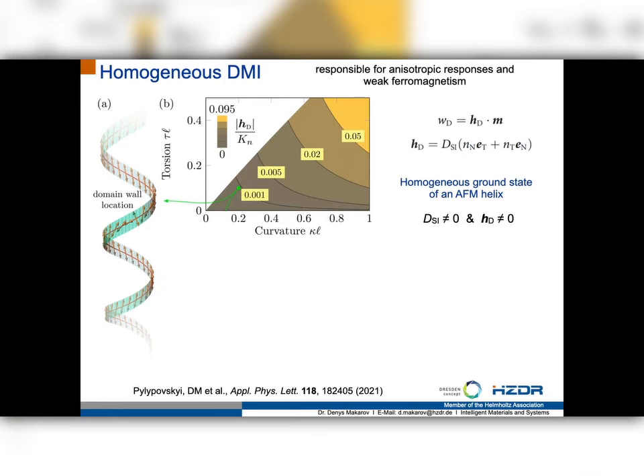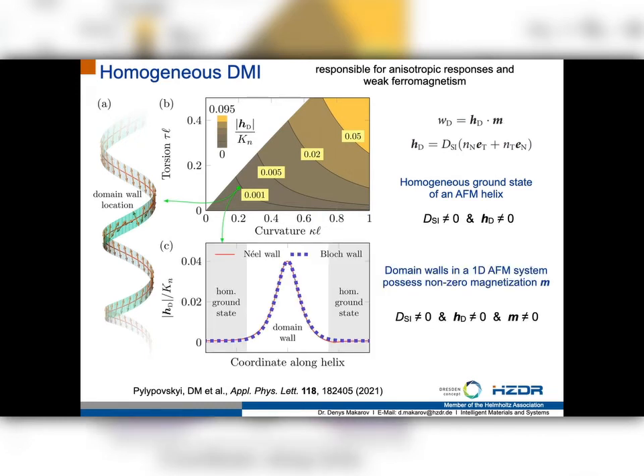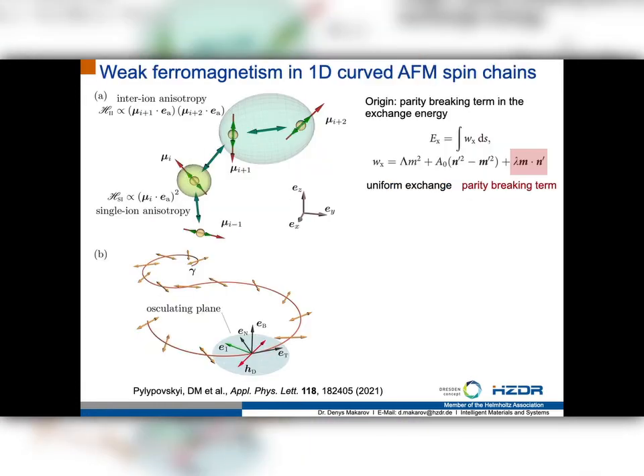As you can see, this effect is not very strong in a homogeneous system, where typically you will have a maximum in the order of 0.1% up to 10% of the anisotropy field, but you can enhance it in a one-dimensional system substantially, like orders of magnitude, simply by having a system where you will have also a domain wall. What is interesting about one-dimensional antiferromagnets is that this system supports a non-zero magnetization at the location of the domain wall. And this makes the term in the anisotropy, this omega D, substantial. You have not only the homogeneous Dzyaloshinskii field, but also non-zero magnetization, which makes this term active in the energy functional. And in this case, you can magnify, for example, by orders of magnitude the homogeneous Dzyaloshinskii field at the location of the domain wall, and make its impact very, very significant on the behavior of the system.